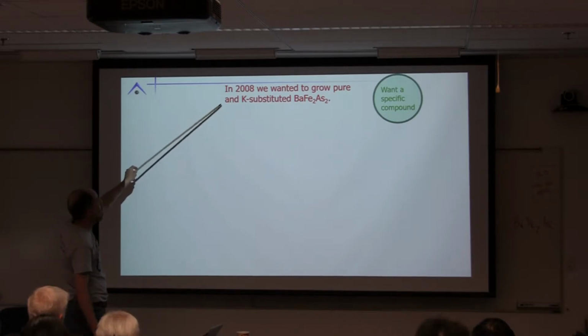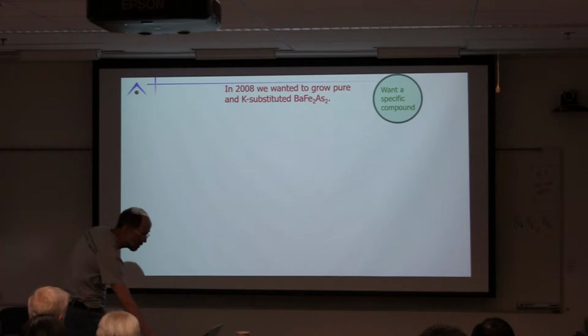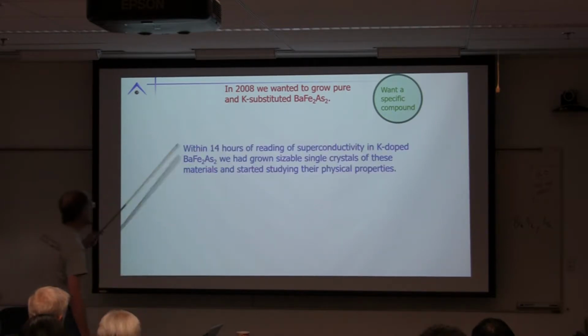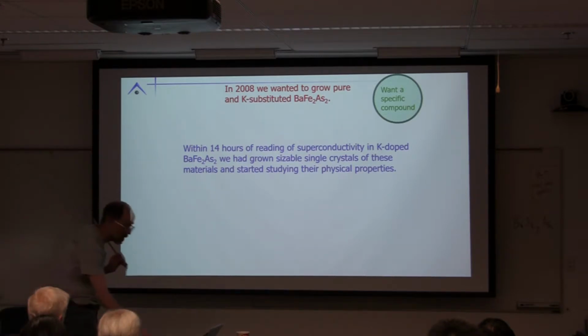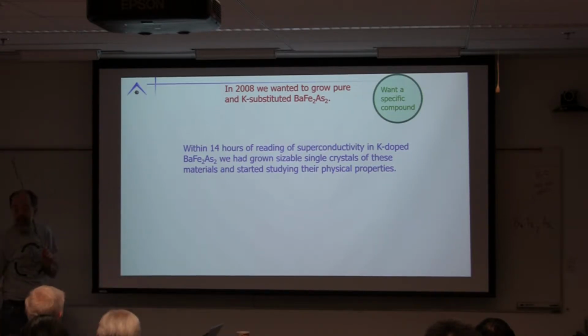So, 2008, we really, really wanted to grow potassium substituted barium iron two arsenic two. Within 14 hours of reading that this could superconduct in polycrystalline form, we had grown sizable crystals and were studying its properties. It was obvious you could grow this out of tin. It's obvious if you add nutmeg to a white sauce, it'll taste better. No, if it's not obvious to you, you don't cook enough. If it's not obvious that you grow it out of tin, you haven't done flux growth enough. But if you've done it enough, it's obvious.